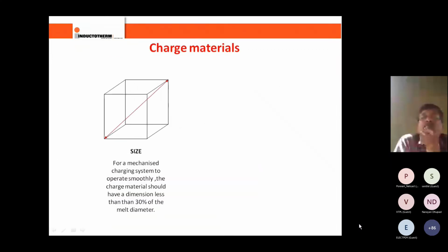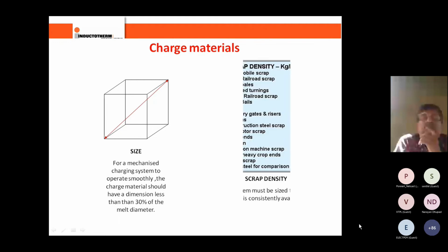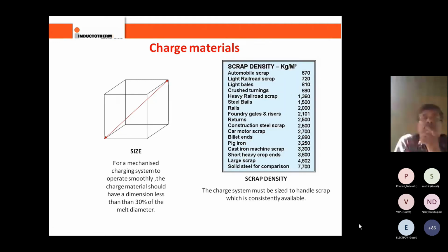When you're talking about E2, the efficiency of this charge material or scrap, for a mechanized charging system to operate smoothly, the charge material should have dimensions less than 30% of the melt diameter. So generally, I'm just illustrating the scrap densities of the various varieties of scraps.